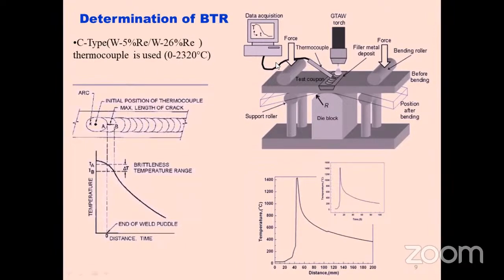For this experiment, we use a C-type thermocouple because we are putting the thermocouple in the fusion zone, where the temperature can be very high, a few thousand degrees Celsius. The maximum crack length we determined from the Varestraint experiment, the MCL, is superimposed on the temperature gradient profile obtained from the cooling profile by inserting the thermocouple. So we take the maximum crack length and impose it on the thermal gradient, and from this we determine the initial temperature at the fusion line as well as the temperature at the crack tip.